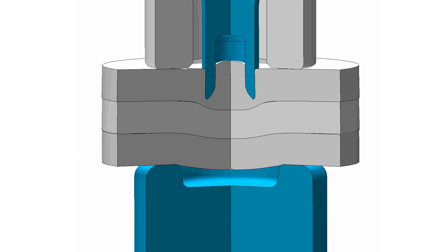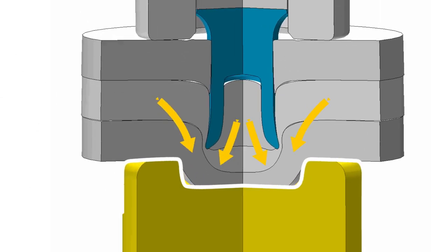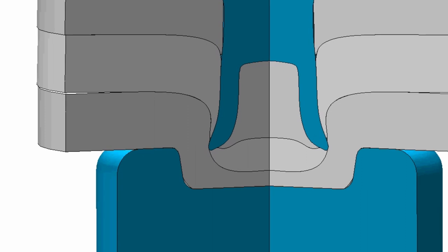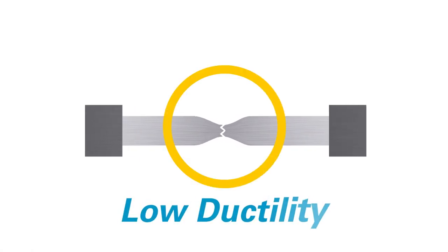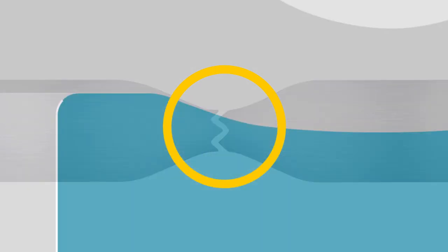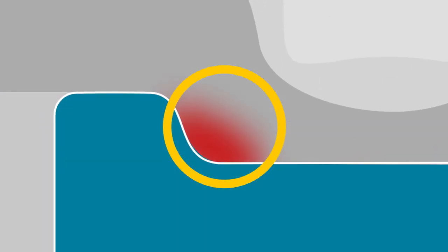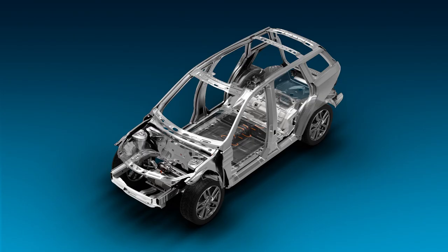Conventional semi-tubular rivets require a deep die to accommodate the material displaced by the rivet. However, high-strength aluminum alloys do not have the ductility for deep dies. The ideal joining approach is to use a suitable rivet to prevent non-uniform flaring and a die to avoid button tearing, all leading to a consistent joint quality in safety-critical areas.